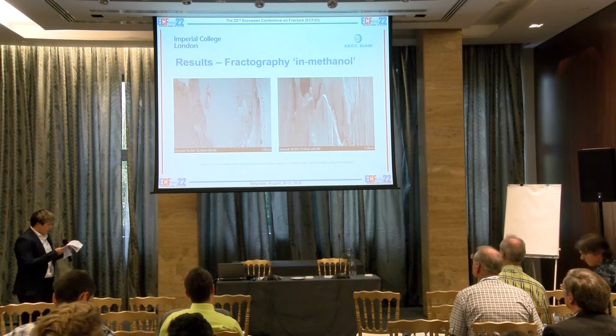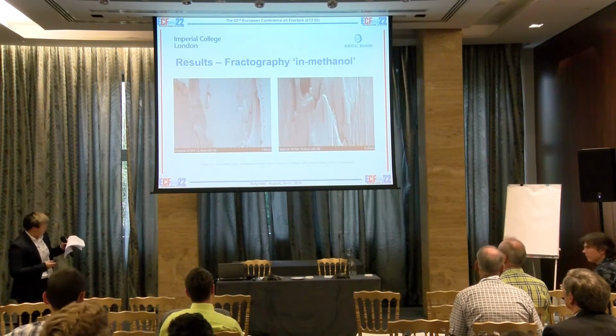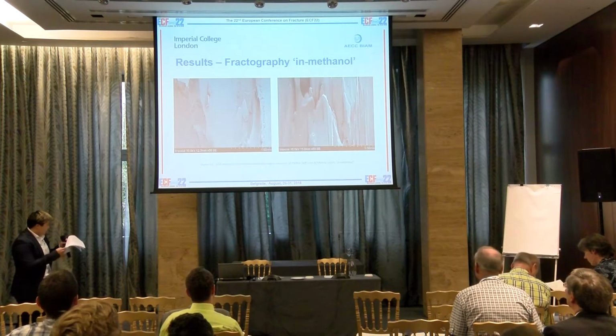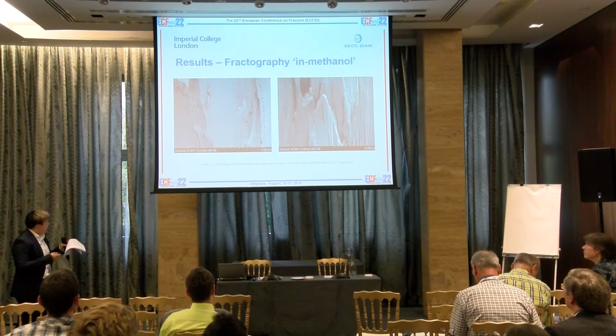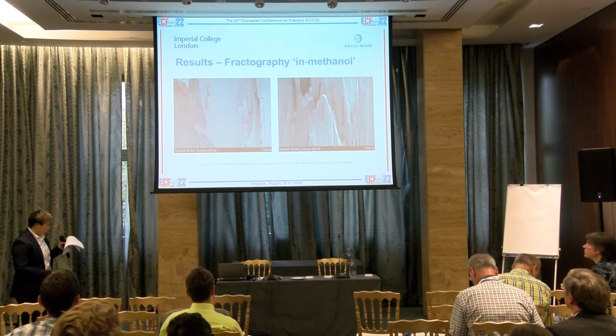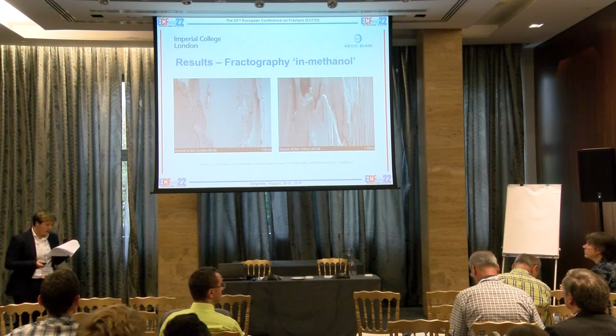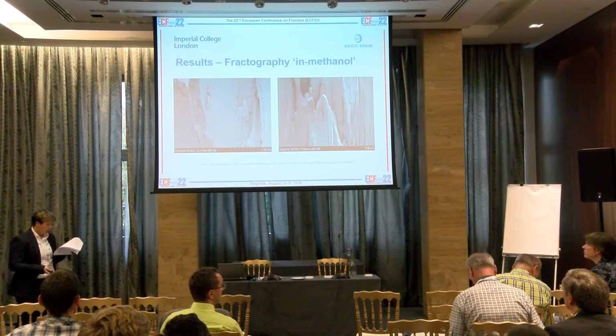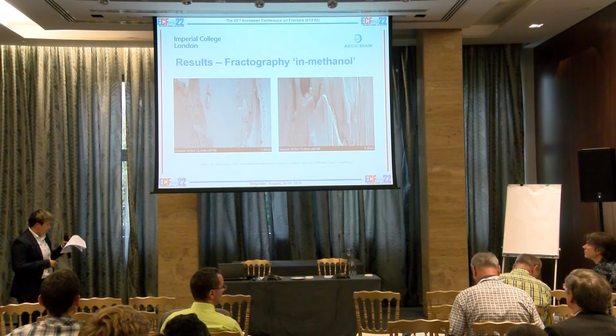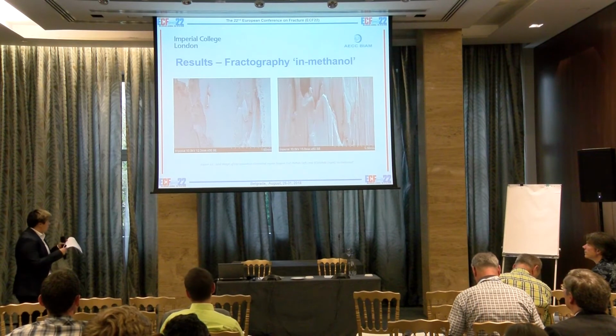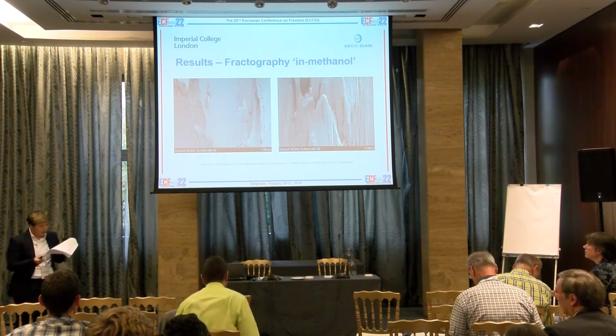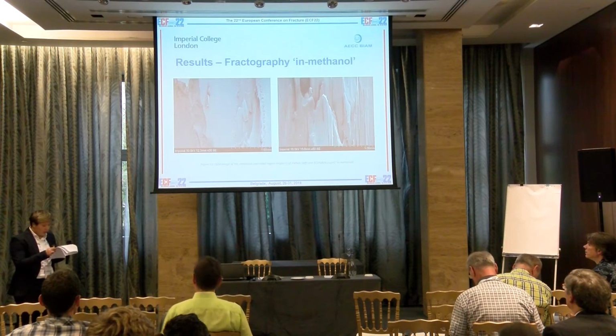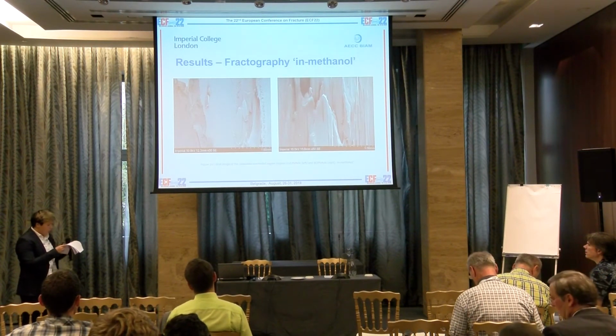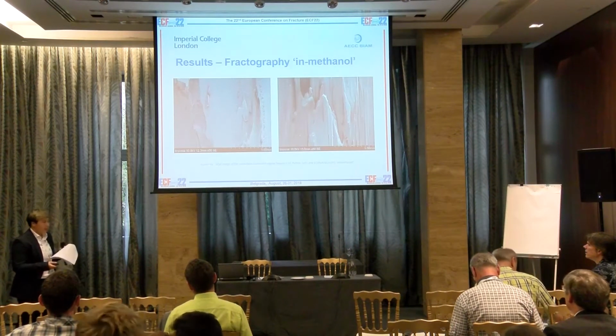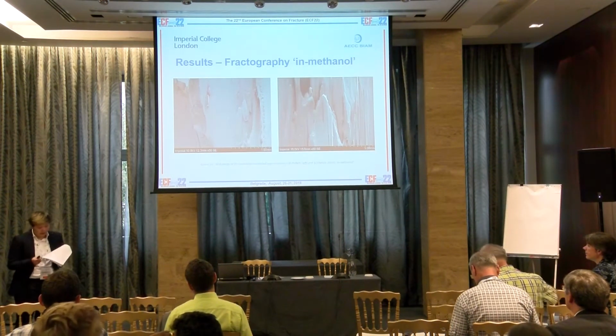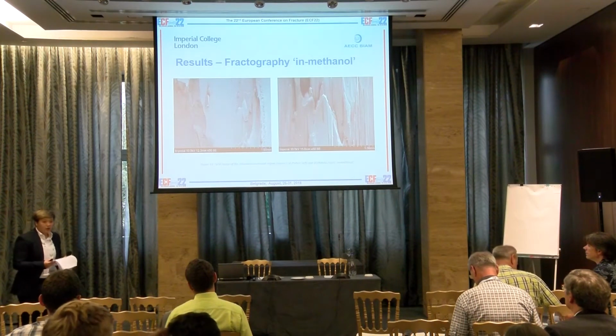And here we have the images for both polymers in methanol. The SEM image from BO-PMMA shows a high alignment along the direction of crack growth, which may suggest a high degree of polymer chain alignment from the stretching process, and appears to be significantly rougher in comparison to the amorphous PMMA, which agrees closely with and is reflected by the increase in fracture energy required for crack initiation and propagation during ESC, as more energy is required to generate a larger, i.e. a rougher, fracture surface.